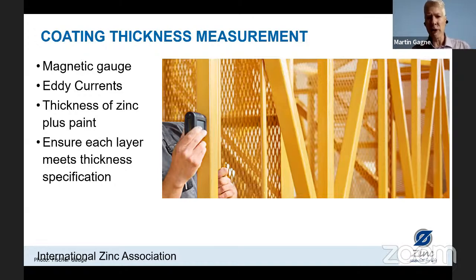And we are finding one of the common errors is the paint is applied too thin. So using an magnetic gauge, they measure a coating thickness. It's the zinc and the paint combined, but the paint contractor may only think that he's reading the full thickness of the paint. So it's important to know the thickness of both coatings. And some thickness gauges now can differentiate between the metallic zinc and the paint on one reading.